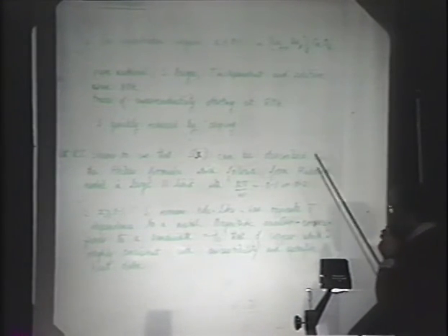0.2. Then for concentrations X bigger than 0.1, or 0.2 in some people's language, S remains hole-like and has opposite T dependence to a metal. Its magnitude is smaller, and it corresponds to a bandwidth about 1/10 that of copper, which is roughly consistent with susceptibility and specific heat data.